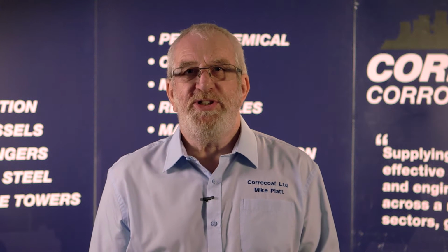When testing, it is simple to say how much material loss is achieved over a given period of time. However, in real life, what is causing the abrasion and defining that is a different subject and very difficult to define. When you think about a particular circumstance, abrasion may be caused in a dry or wet environment by particles that are large or small, or a combination of both. The impingement angle can vary significantly, as can the angularity and hardness of the particle. Temperature will play a part, as will the corrosivity of the environment. A very large amount of variables and permutations to assess.